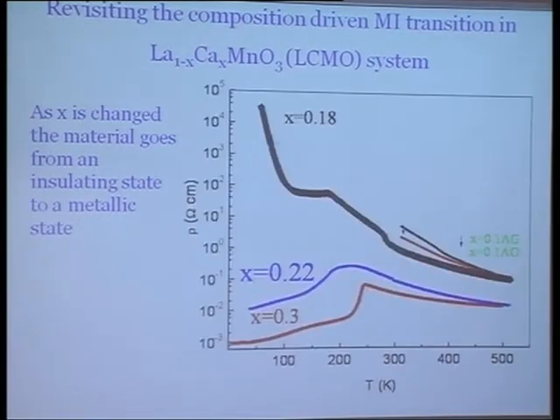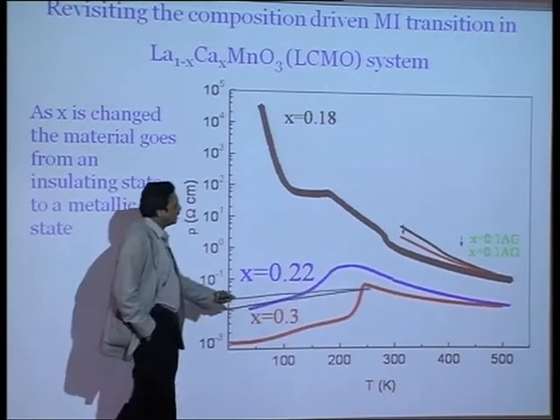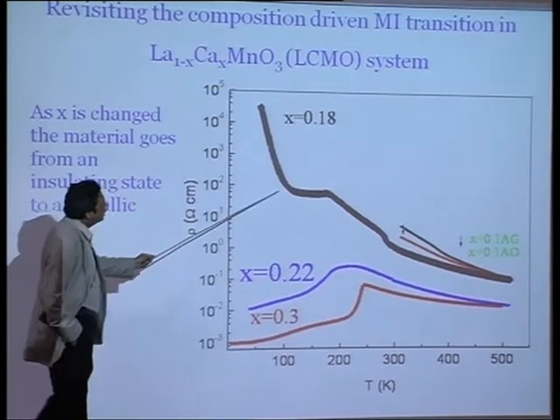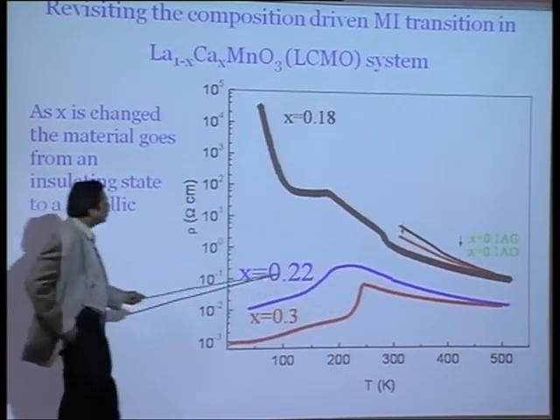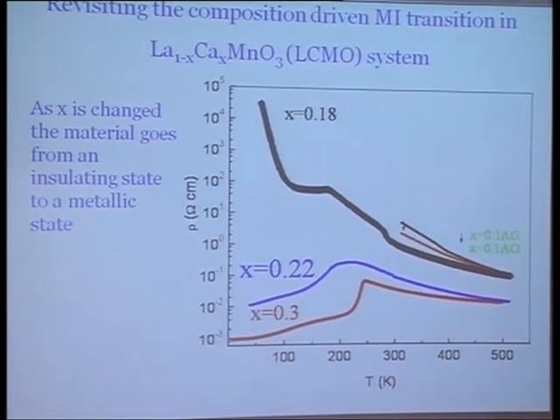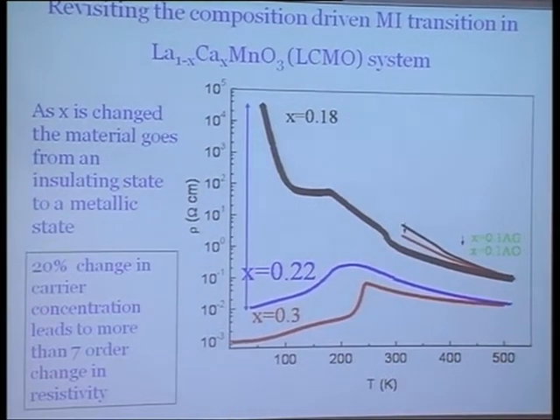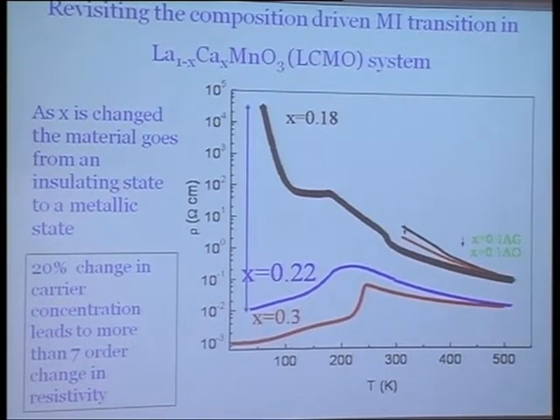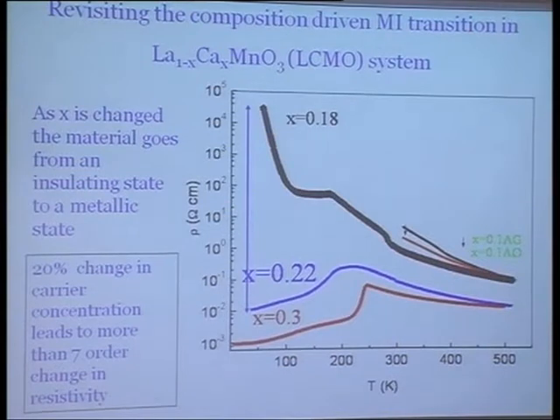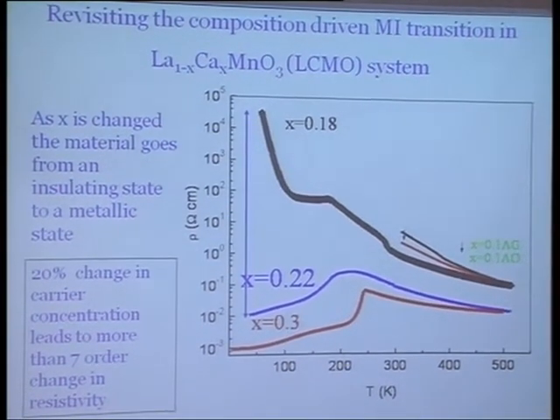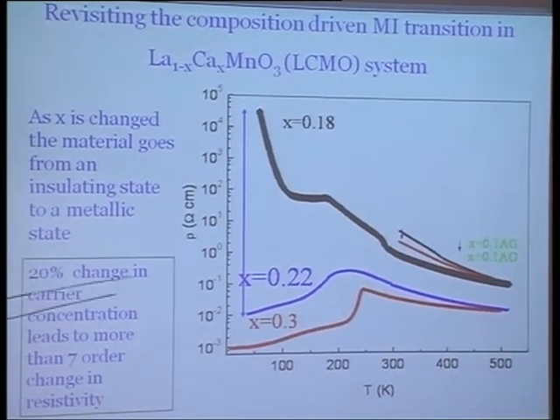Now if I look into this hole doping and the variation in the resistivity and all these things in the manganite system, the question is, can I bring in the language of insulator metal transition? So let us just look into some data. These are three single crystals. This is the one very metallic system where you see colossal magnetoresistance. This is the insulating one, and this is the one which is lying at the critical region of the insulator metal transition. And you can see that a mere 20% change in the carrier concentration can lead to about 7-8 orders change in the resistance.